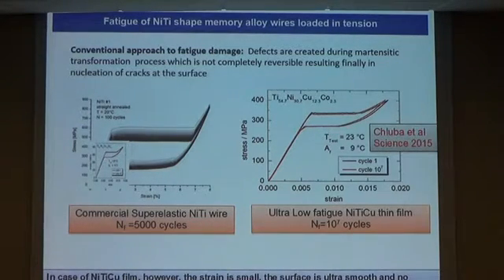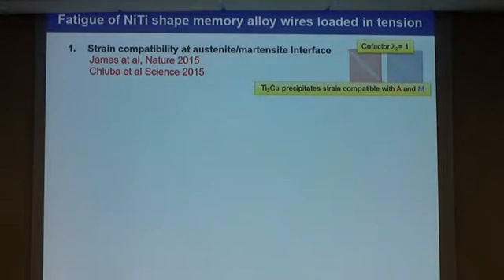There is probably a chance to reach such kind of high performance nitinol, but there are difficulties. So maybe I can go again. I can think about what kind of difficulties we have. So one of them is this compatibility on the lattice level. And these people in science, they claim actually that if you have precipitates which are strain compatible with austenite and martensite, they strengthen the material but don't prevent the phase transformation. You can reach such kind of stable behavior.